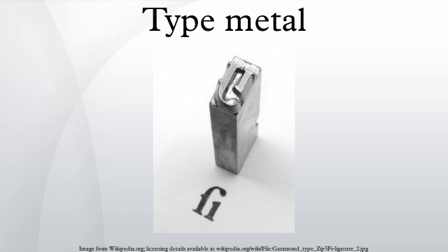Using a 10% antimony, 90% lead mixture delays lead crystal formation until approximately 260 degrees Celsius. Using a 12% antimony, 88% lead mixture prevents crystal formation entirely, becoming a eutectic. This alloy has a clear melting point, at 252 degrees Celsius. Increasing the antimony content beyond 12% will lead to predominantly antimony crystallization.